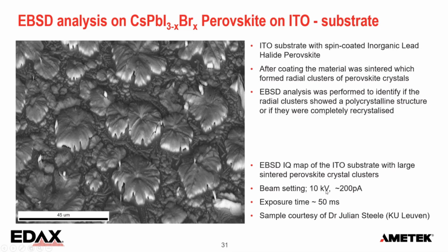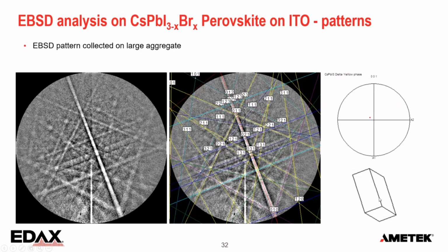Now, also here, around 10 kV, 200 picoamp, 50 millisecond exposure. And the first thing I had to do was try to find some patterns just to see if I could index this. Now, pattern quality is pretty good. So here we can get nice indexing. I could use this to optimize my reflector table, because if you're familiar with EBSD, we need to apply a structure file or a reflector table for indexing.